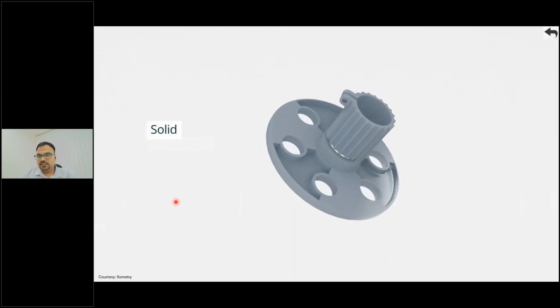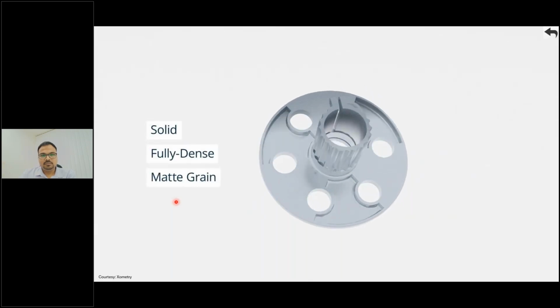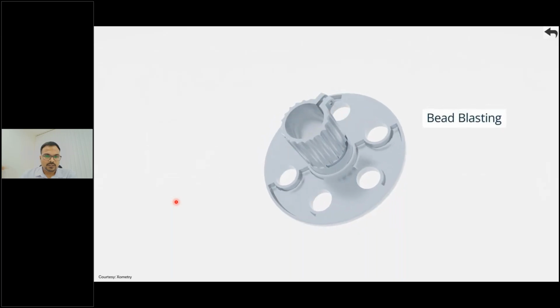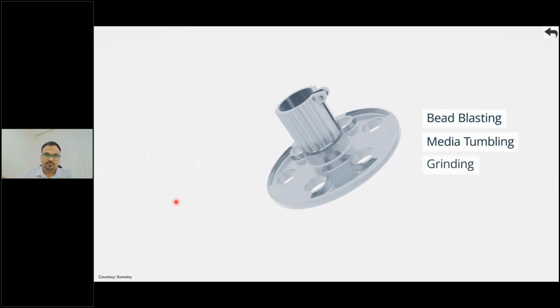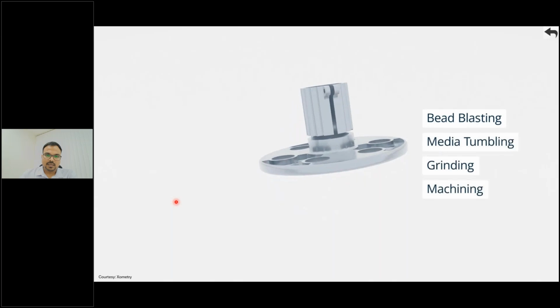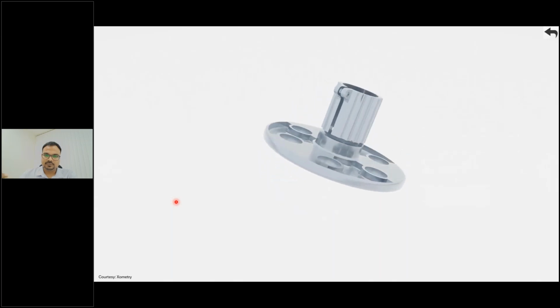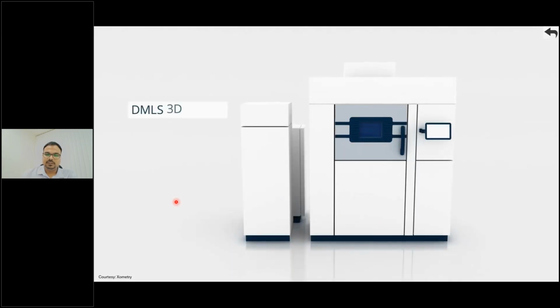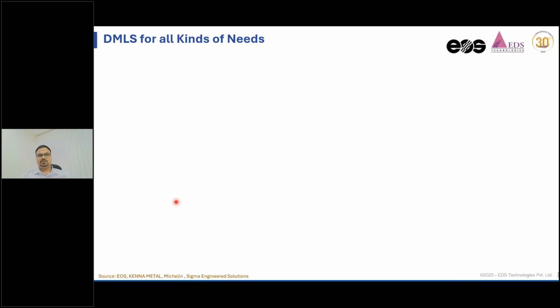So these materials are directly machinable. You can do EDM, you can do wire cut, you can perform, in fact, any kind of post processing. You can do even hardening after the printing is over, after the heat treatment is done. You can do further hardening process of the material to improve the surface hardness.